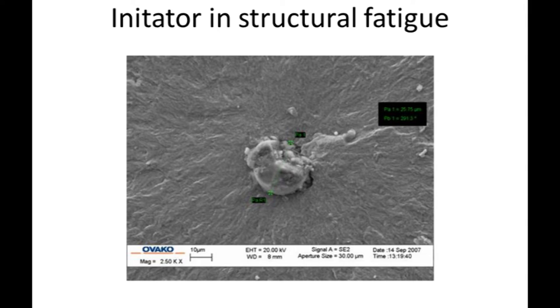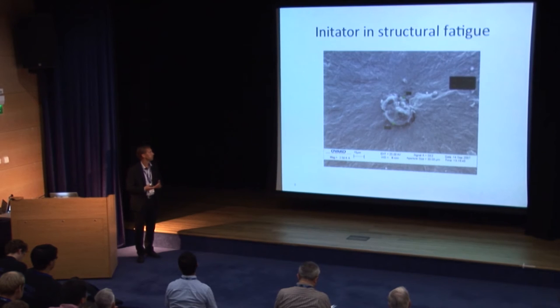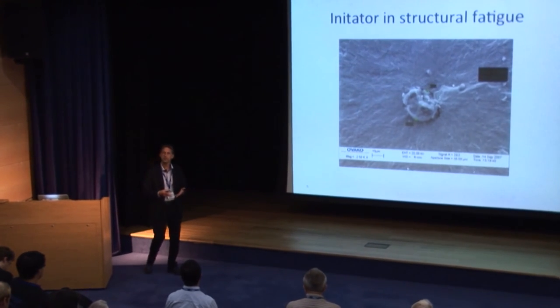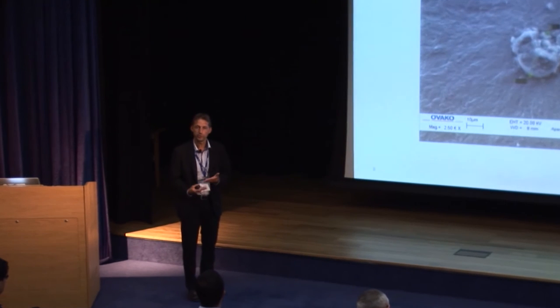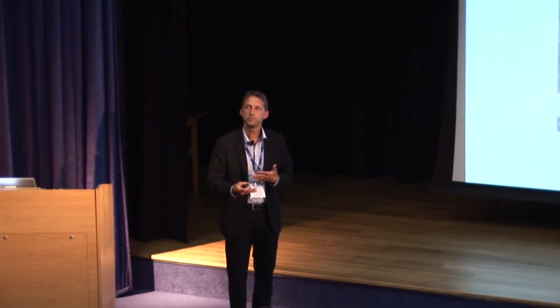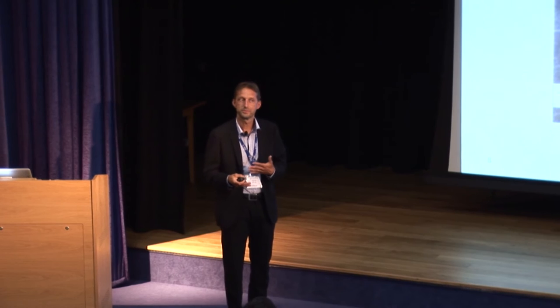There are other ways of fatigue testing. You can make structural fatigue. I think it's the same mechanism. It looks different, but if you have a good eye, or if you sit at the microscope, you can see the same kind of phenomenon. You have some kind of breakdown of the material in the vicinity of the defect, making it fracture. So you decay the material until you reach the fracture strength where you create a crack. And then you can start to play around with the fracture mechanics.